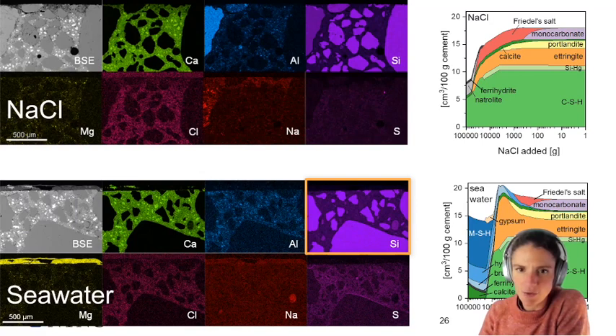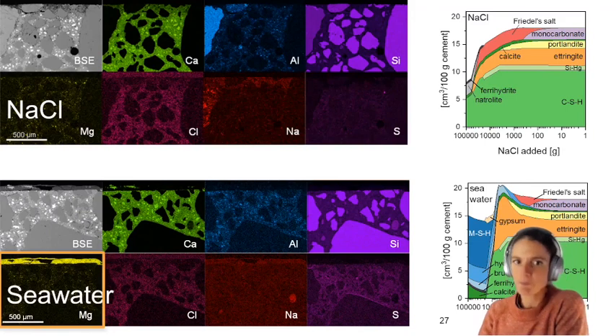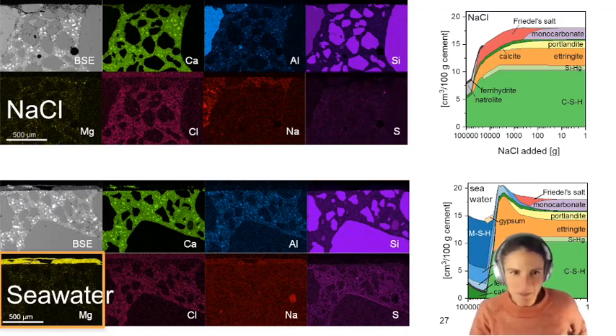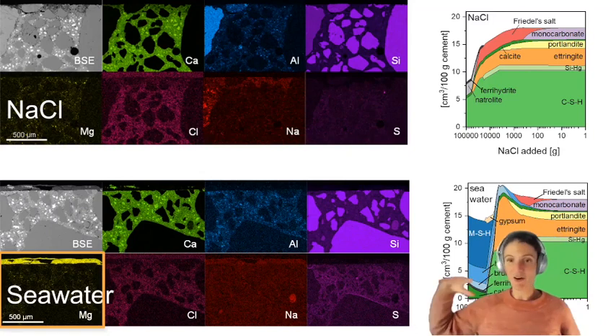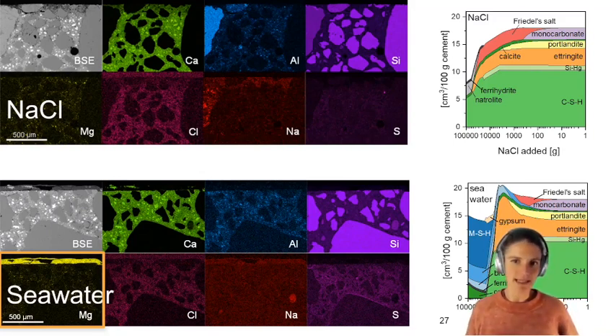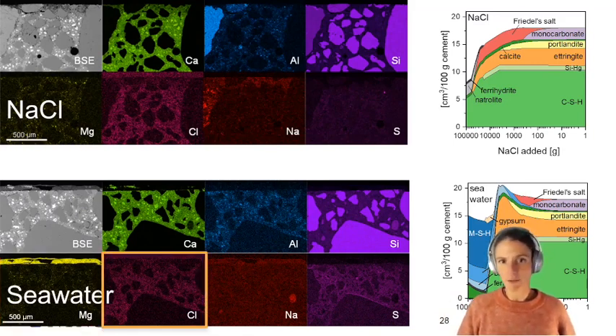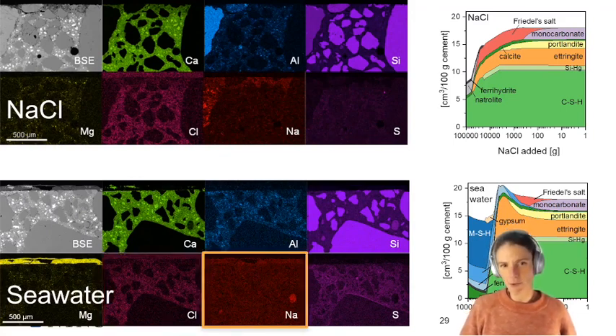Silicon, again, a good illustration of what are the sand particles, which are rich in silicon. And then here we have the magnesium. That's quite interesting because we see like a carpet of magnesium on the surface. So this is brucite precipitation on the surface. We don't really see MSH yet, and we think that is because that takes some time to form. But we do see a clear brucite enrichment. Then chloride enrichment in the cement paste, as expected. We don't really have a sodium enrichment in the cement paste. There's some sodium in the brucite precipitated layer, but not really in the cement paste.